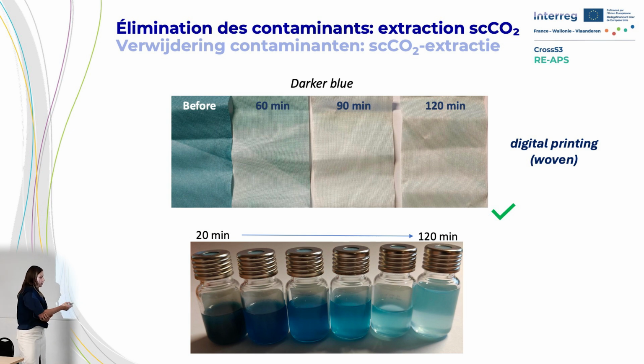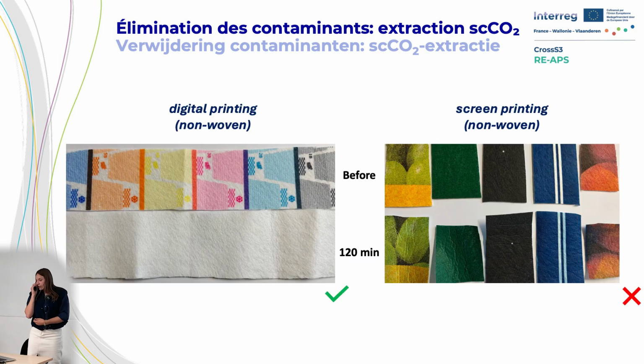Here we took samples of the extracts from the supercritical CO2 machine. You see that it's very dark blue, and with longer extraction times the extracted color becomes less. So probably by extracting longer, the textile would become even whiter. So this was already interesting. We tried other materials. Here we tested a digitally printed non-woven textile. This had a good result.